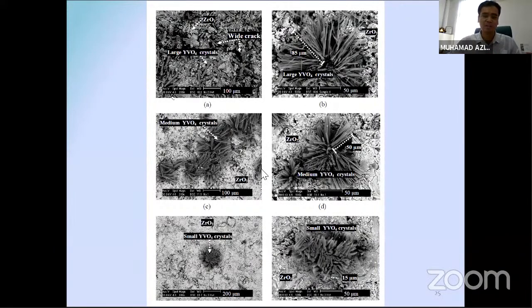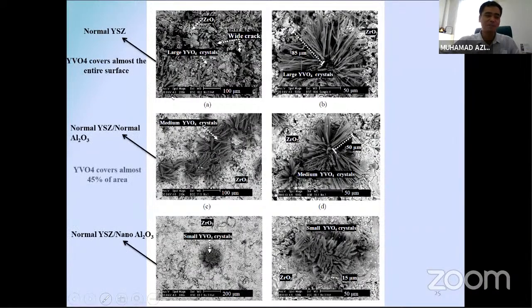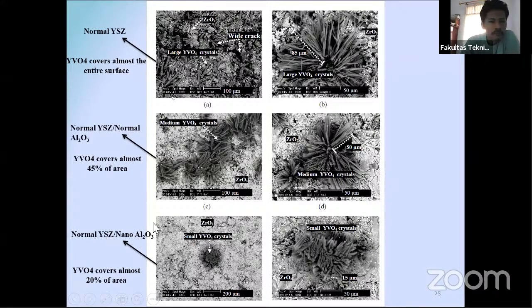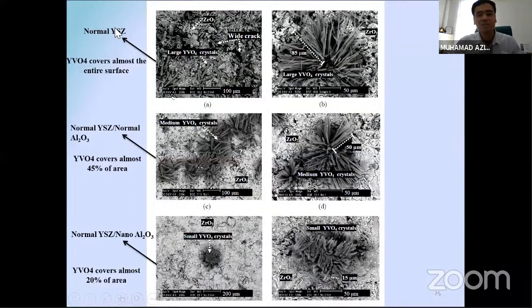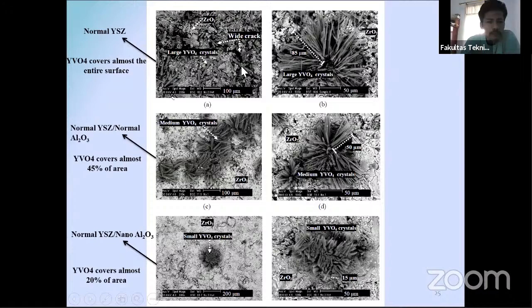We don't want this. That's why in our research, we try to reduce the possibility that will create the vanadium pentoxide. We can reduce up to 20%, meaning that if you have another layer, for example an aluminum layer, you can reduce 20% compared to without another layer, where you have it all over the surface. You will see the salt vanadium pentoxide react with the yttria, meaning that you lose the structure of yttrium because yttrium already reacts with the salt. You lose that. So we don't want this to happen, so with another layer.